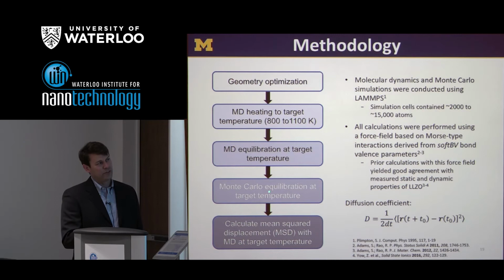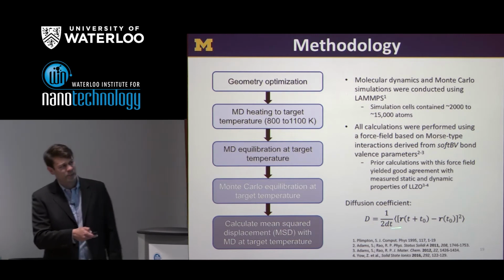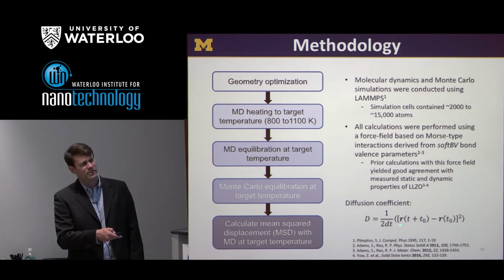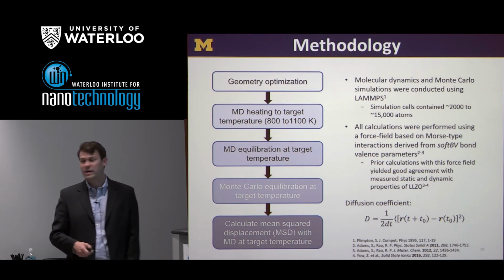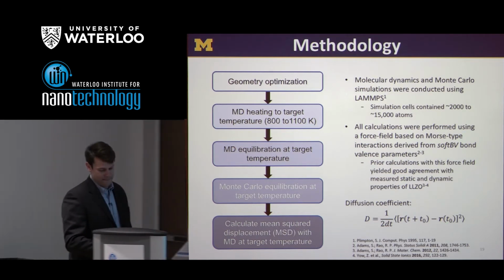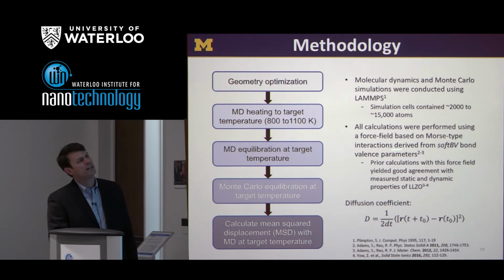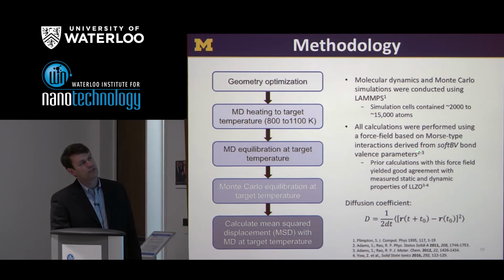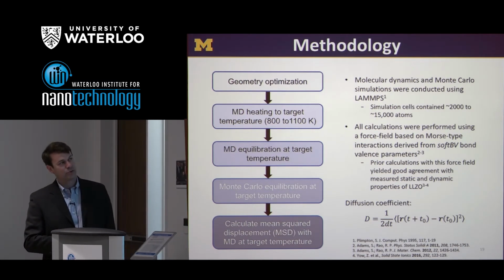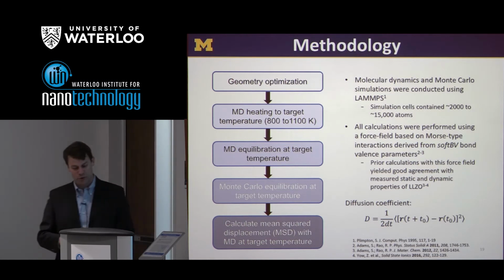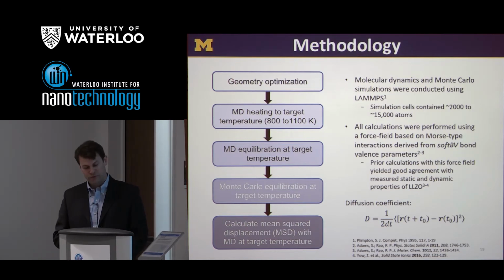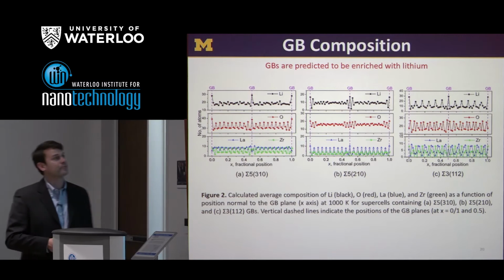And then finally, we take those structures, those equilibrated structures from Monte Carlo, put them back into molecular dynamics, and ultimately get out the diffusion coefficient, which is based on the mean square displacement, the average mean square displacement of all of the lithium ions in the cell. And so for this, we're using a so-called Morse-type soft BV interatomic potential, which is from Stefan Adams' group in Singapore. So this has already been used a few times to look at LLZO.